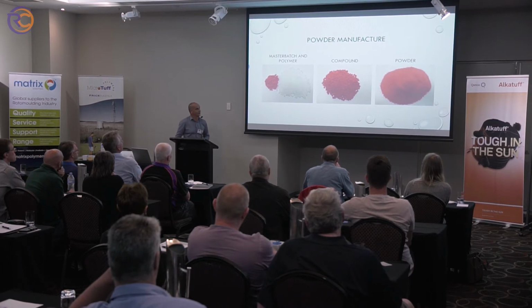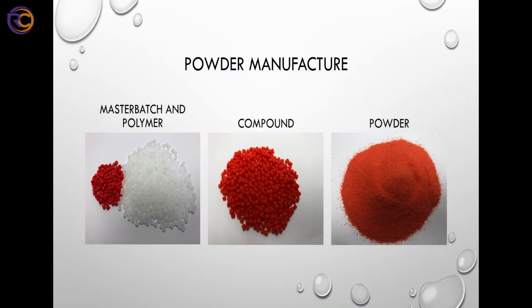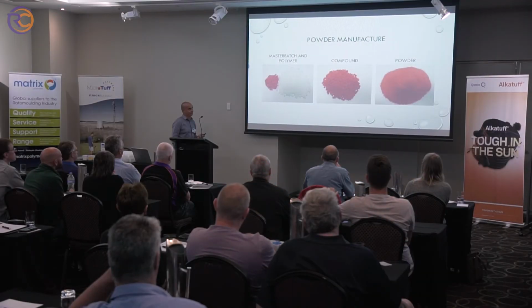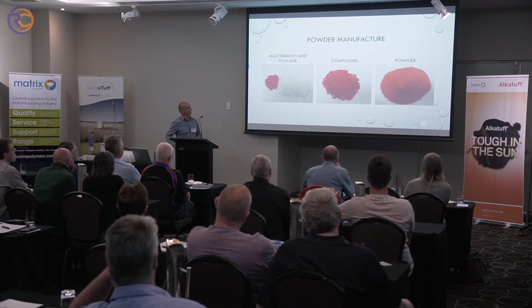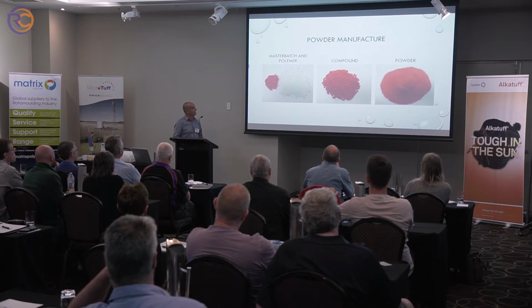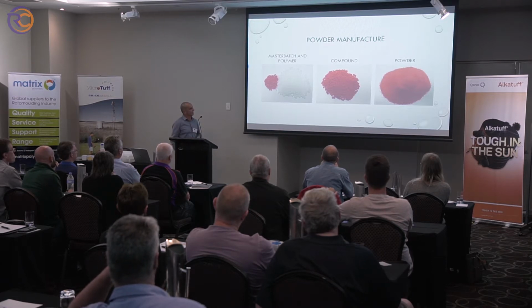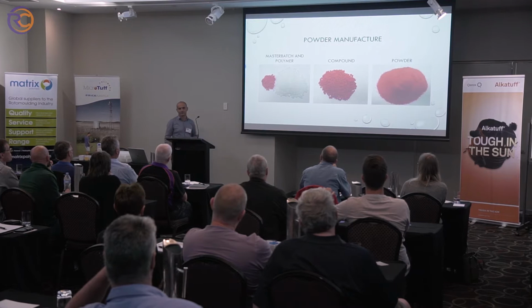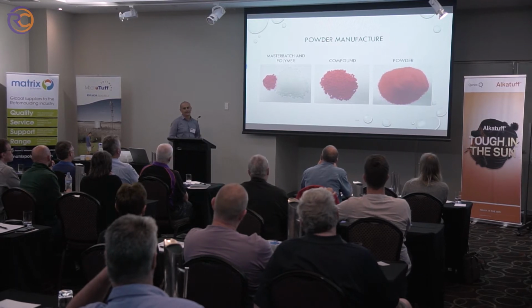So, just talking about the 3 stages. We have here, this is what goes into the extruder. Now, sometimes people refer to compounding as extrusion, pretty much the same thing. But before we actually compound the material, we use a master batch, which is a concentrate of pigments and other additives. And that master batch is in a carrier. A carrier could be the same resin that is going to be compounded into, or it's a material that's very good for dispersing the pigments and additives that you want to put in.